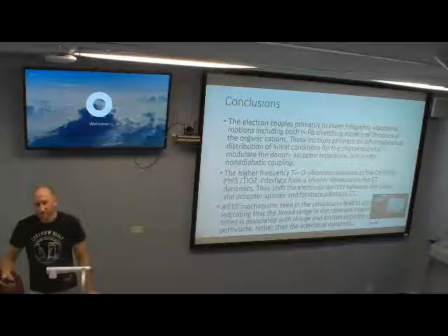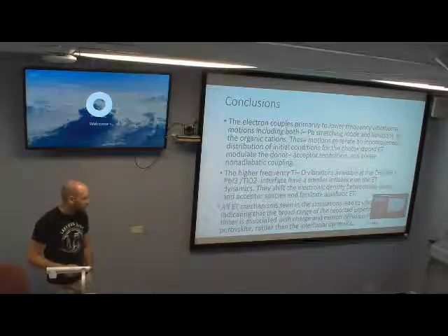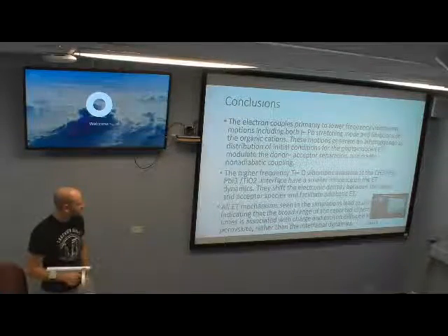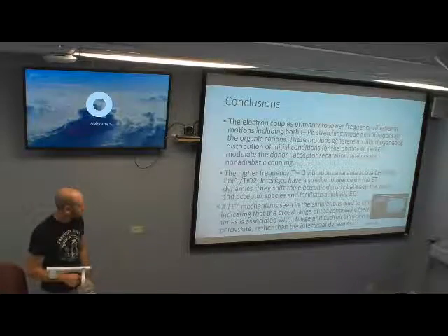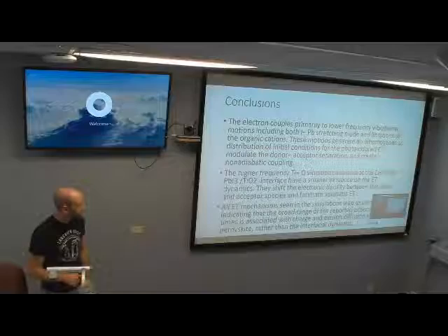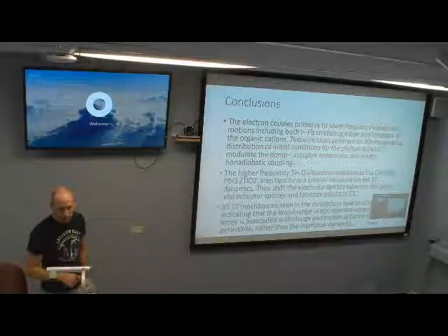And here they give this analysis of these different bonds, written in a more clear way. It looks like they differentiate between the iodine-lead contribution to the frequencies, the iodine-lead bond versus the titanium-oxide bond. And I might be wrong, but it sounds like these titanium-oxide vibrations contribute insignificantly to the charge transfer processes.